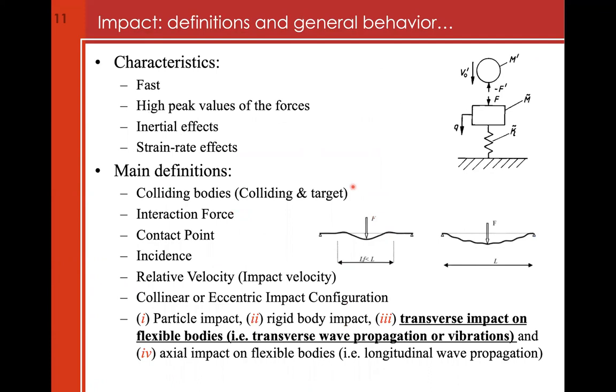Why am I combining these two topics today? The idea is to understand how to use green materials for impact resistance. Green material research is not new — it's an old idea with full research behind it. But we can combine the good performance of recycled or green concretes for impact. Under impacts or explosions, everything is very fast: there are high peak force values, non-negligible inertial effects, and in particular a strain rate effect — a variation of the mechanical behavior of the material due to the fact that we are applying the load fast.